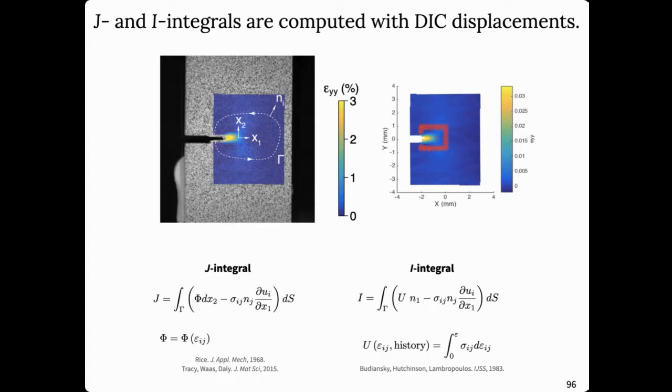Yeah, it's a fun space to work in. When we know it's not linear elastic fracture mechanics, we see what we can do, and we're trying to get these results going with the data. We have a code that will compute the J integral from the DIC displacements, and others have done this before as well. But for now, we're just using that proportion, the K over K max. I can tell you study fracture a lot, Rami.